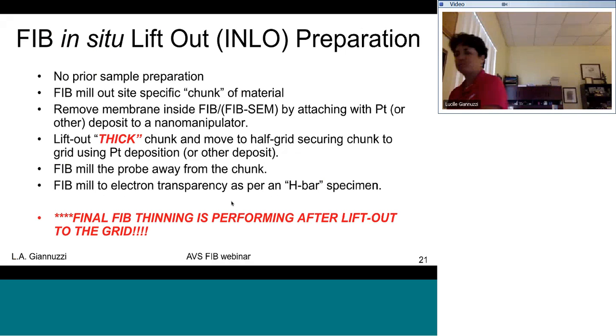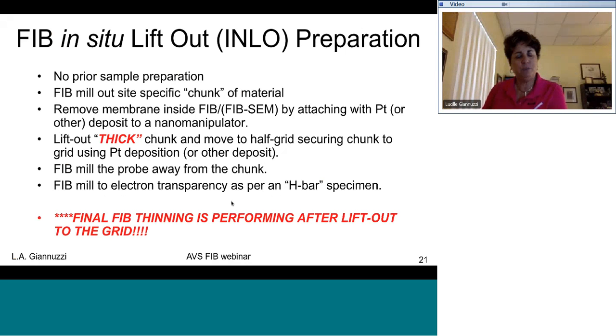Okay. So in situ lift out is a way to basically get a site-specific sample FIB milled, lift it out inside of the FIB, and then final FIB prepared. Once you get this chunk of material on a grid, then the rest of the FIB specimen prep is just like the H-bar technique. Okay. Key here is that final FIB milling is performed after the lift out to the grid.